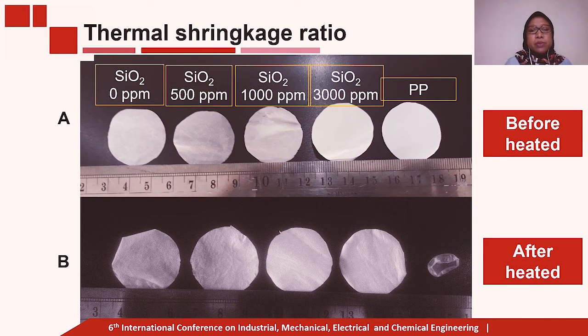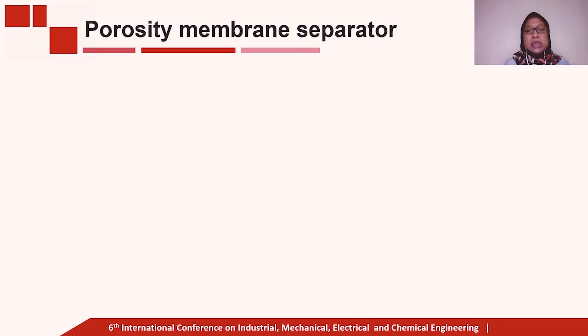This photograph shows to us the nanofiber membrane. PVDF SiO2 nanofiber with different SiO2 content and also polypropylene as for comparison. Before and after heating at 160 degrees C for 30 minutes.